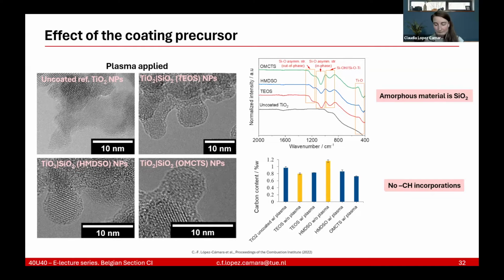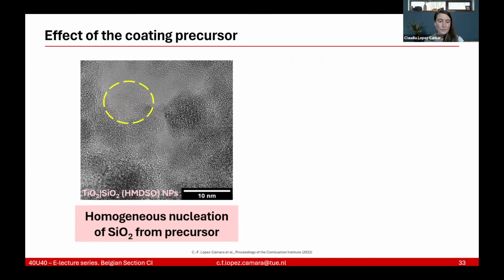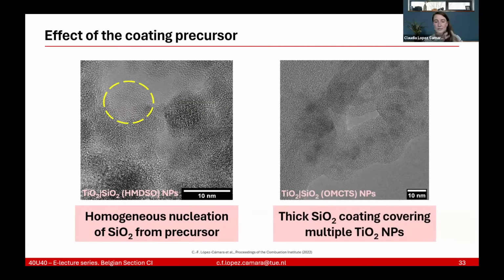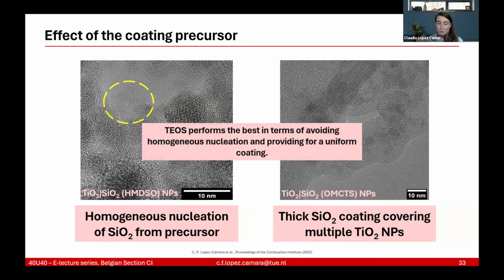Therefore, we looked into the TEM a bit more. And for the HMDSO case, we saw that we had homogeneous nucleation of the silica from the precursor. That means that we were creating nanoparticles that did not have titanium oxide inside, that were just silica nanoparticles. And that's something that you want to avoid. And for the case of OMCTS, we saw this thick amorphous structure of silica coating and covering multiple titanium dioxide cores, which is, of course, not something that is desired. Therefore, we concluded that the most desired precursor for creating the silica shells is TEOS, as it performs best in terms of avoiding homogeneous nucleation and still providing a uniform coating of the titanium dioxide cores.